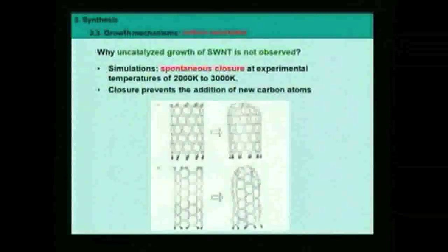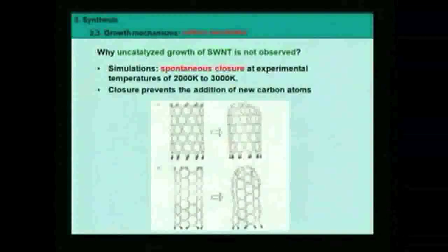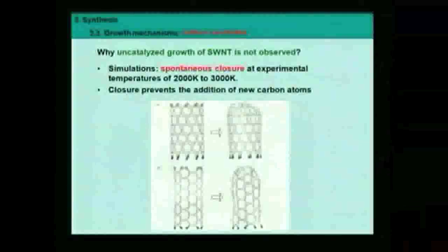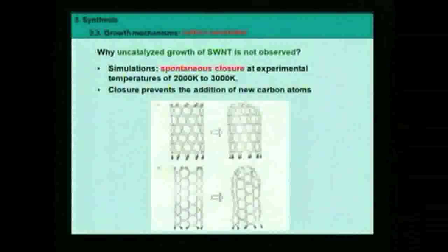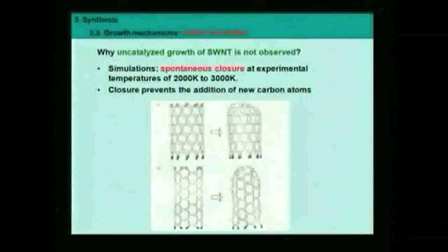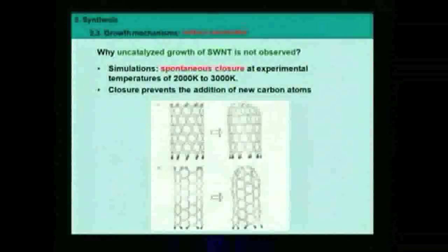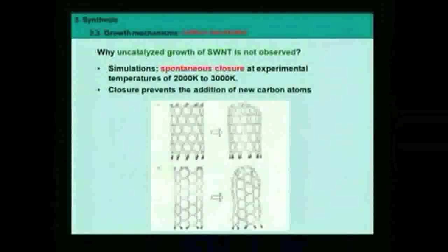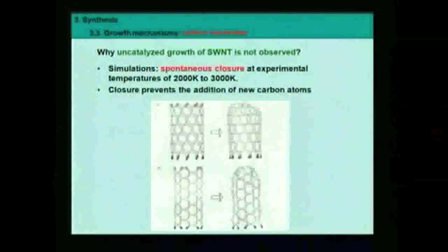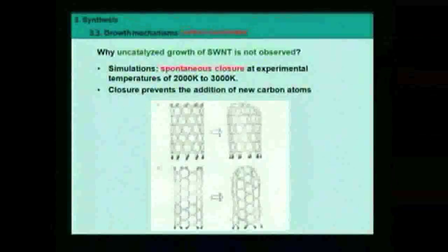Okay, first thing, why is uncatalyzed growth of SWNT never observed? To explain that, there were many simulations taking a tube with open ends and heating it. What people observed during simulations at high temperatures close to the temperatures actually used for the growth is that this end will spontaneously close, as you see here, and another example is shown here. It means that an open end is not stable. If you increase the temperature, it will close by itself. This is the main explanation presently for why it is not possible to grow single wall nanotubes without catalyst. You need something here to stabilize the opened end.